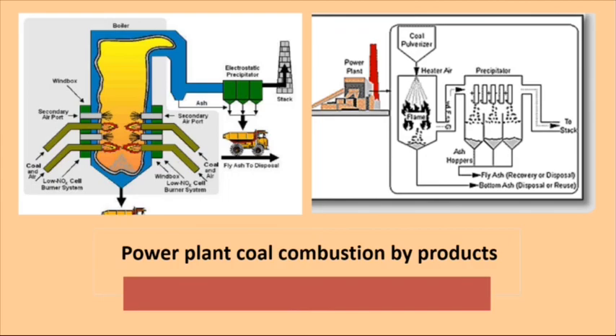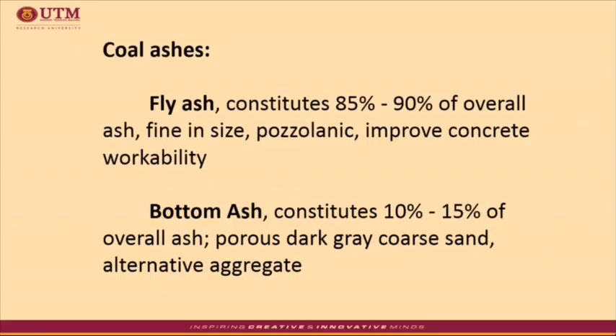So what are the unique properties of these coal ashes? For the fly ash, it constitutes about 85% to 90% of the overall ashes. The fly ash consists mostly of silicon dioxide, aluminium oxide, and iron oxide. It's pozzolanic in nature, reacts with calcium hydroxide to form cementitious compound. And that's why it has been used to replace up to 50% of the Portland cement for concrete production and also improve workability and pumpability of concrete. Others, it shows less bleeding and provides self-leveling and self-compacting of the backfill material.